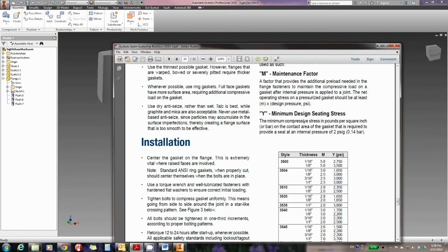So the big important question is what kind of stresses we need to impose, and here we have some values. This is a brochure from a a gasket vendor that we used, and we use these pretty often. And what you're reading here is that in order to hold 2 psi of pressure, we need to be imposing stresses of 3000 psi or so. Okay? And you can tell all of these numbers are in thousands of psi. Okay? So 2 psi process pressure, 3000 psi sealing stress.